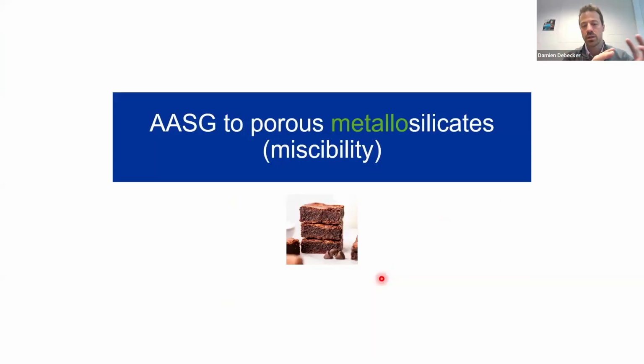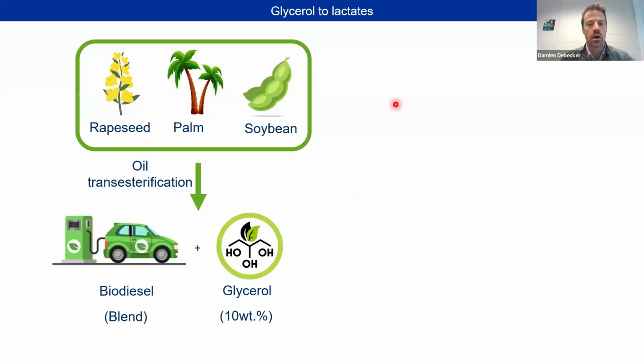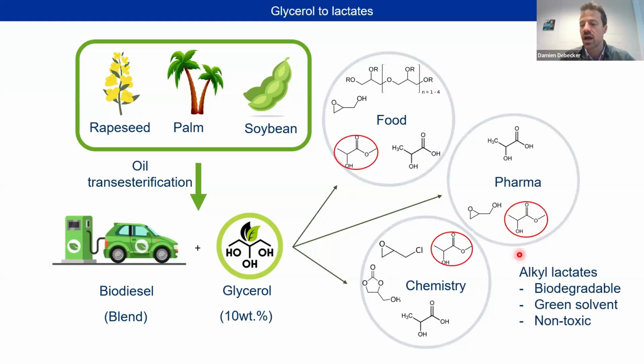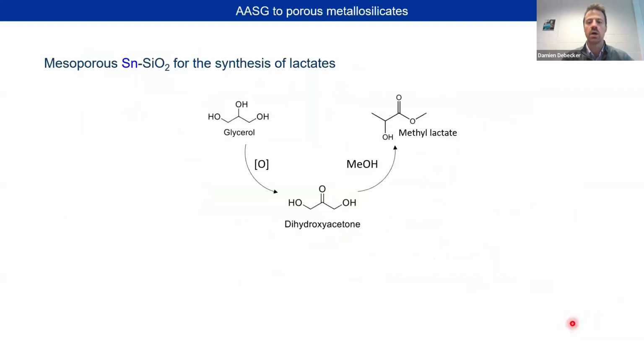So I'll go for the first one, the brownie, where we need the active species to be dispersed in my silicate, as dispersed as possible. I will show you this in the context of the valorization of glycerol. You know that glycerol is a waste from the biodiesel industry, and we have to make something useful with it. And what we're targeting is alkyl lactates, because they're green solvents that are very interesting. So how to make methyl lactate, for example, in this case, you first have to oxidize selectively this OH here to get dihydroxyacetone, and then rearrangement with methanol to get to the methyl lactate.